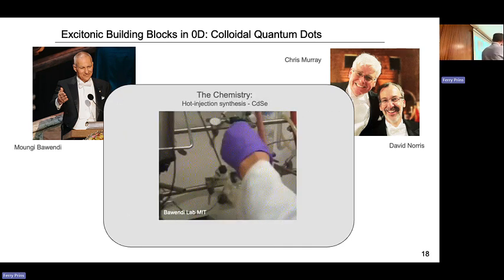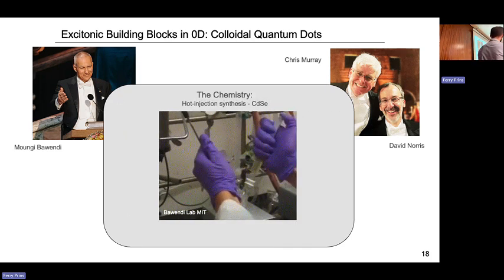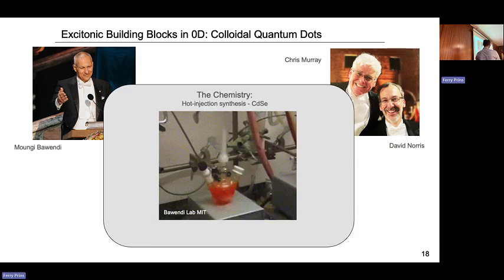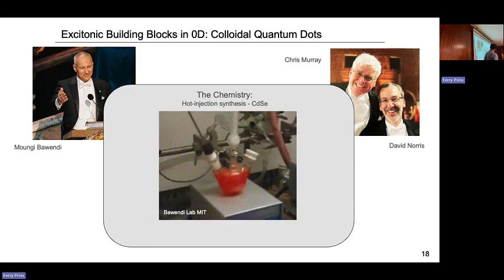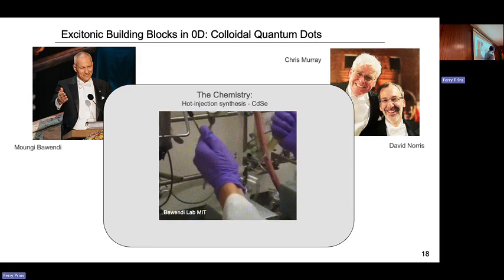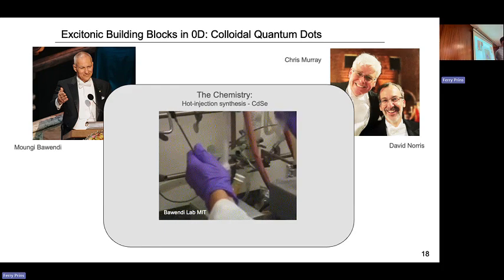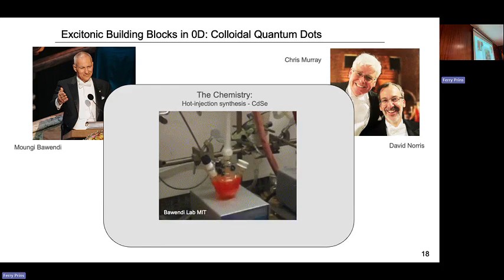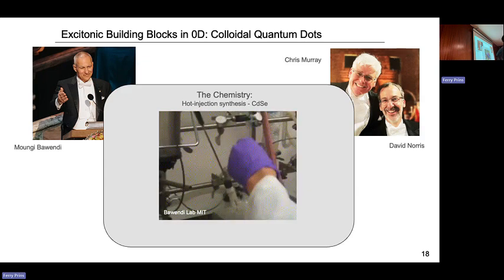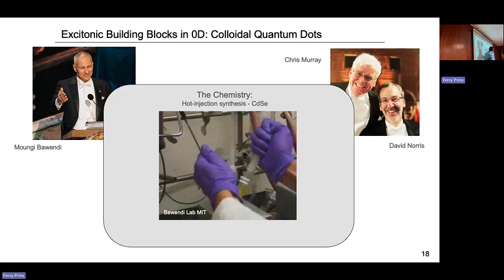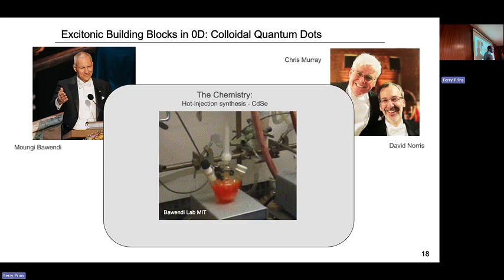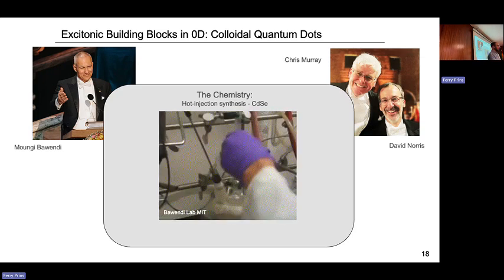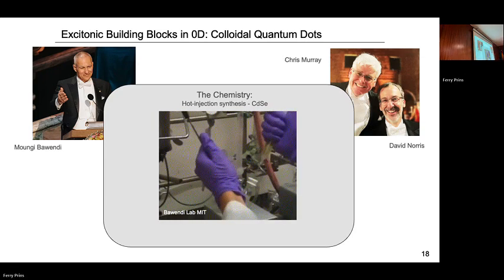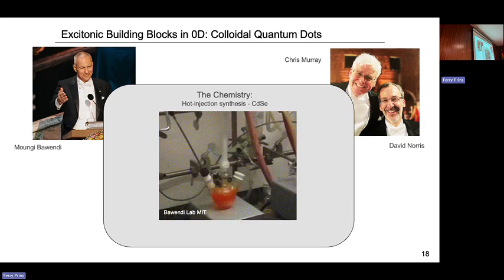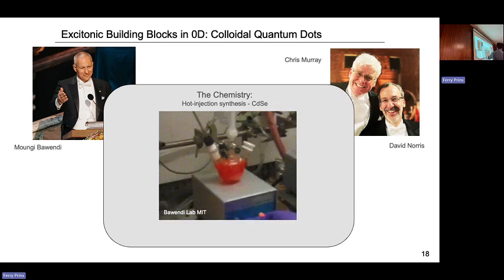The easiest way to explain it is by showing a movie. This is not sped up, this is real time. There's a movie from the Bawendi lab, but basically you have a very hot precursor solution that you just take out of your heating mantle, and very fast you inject precursors, and you get immediately your red color. That is your quantum dot—the red from the cadmium selenide quantum dot.